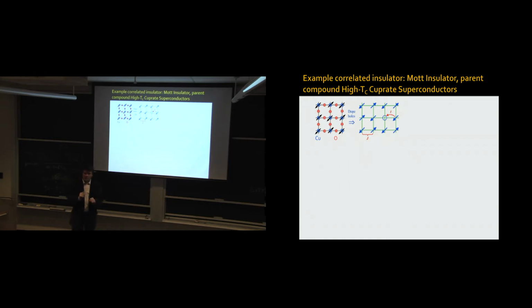Now, an interesting thing happens if you remove a few of these electrons. Because now, if you remove a few electrons, so you dope it with holes, these electrons have empty sites next to them. So they can jump onto those empty sites and go from one place to the other. And they do this in a correlated fashion, which is believed to lead to high temperature superconductivity.